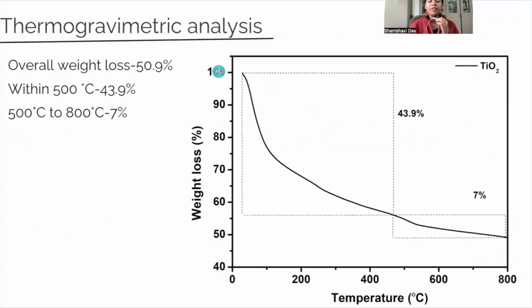Coming to the thermogravimetric analysis, the overall weight loss was 50.9%. However, most of the weight was lost, about 43.9%, within 500 degrees Celsius, and 7% of the weight was lost between 500 degrees Celsius to 800 degrees Celsius. This shows that the thermal properties of the remaining sample above 500 degrees Celsius are pretty good.